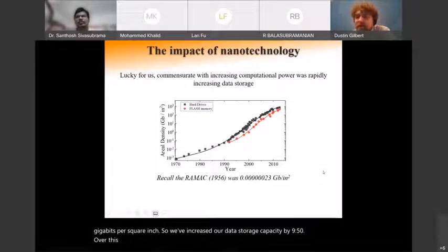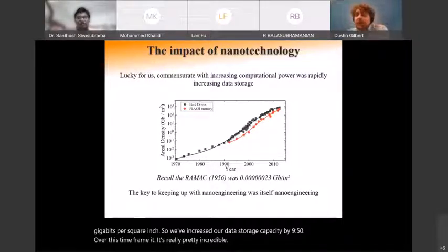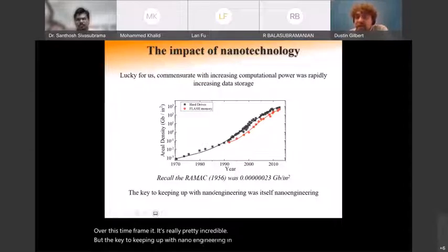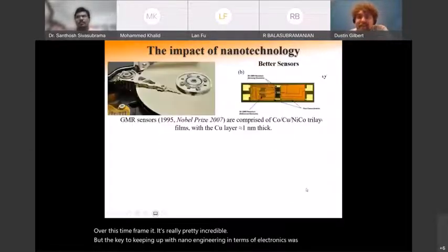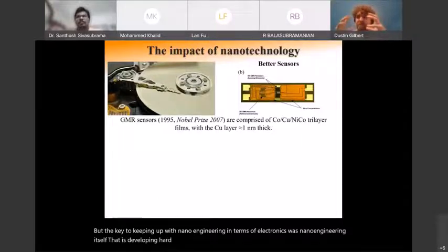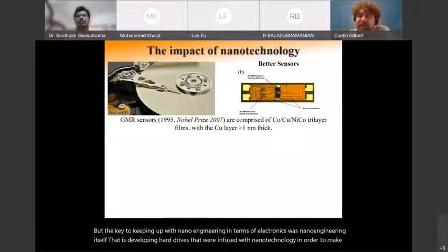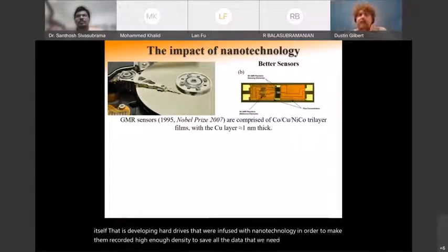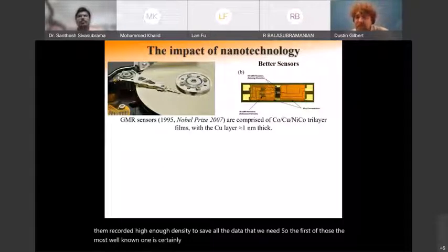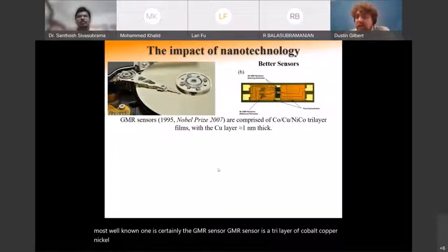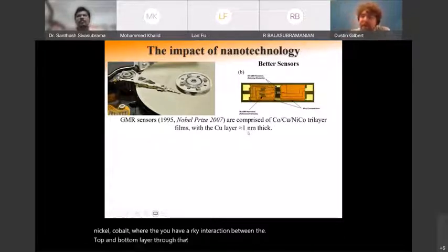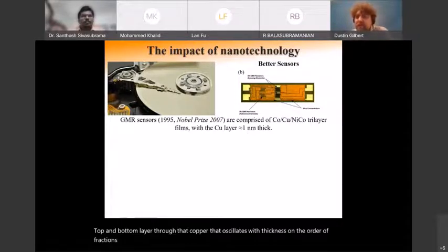It's really pretty incredible. But the key to keeping up with nano engineering in terms of electronics was nano engineering itself. That is, developing hard drives that were infused with nanotechnology in order to make them record at high enough density to save all the data that we need. So the first of those, the most well-known one, is certainly the GMR sensor. A GMR sensor is a tri-layer of cobalt, copper, nickel, cobalt, where you have a RKKY interaction between the top and bottom layer through that copper that oscillates with thickness on the order of fractions of nanometers. And so you have to have control of your copper layer on the order of less than a nanometer.